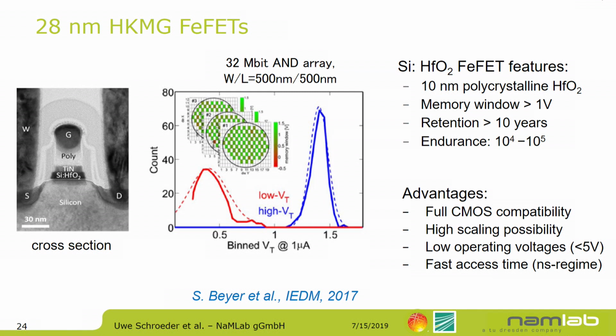And GlobalFoundries did this on 300 millimeter wafers together with Fraunhofer here, and showed that on 300 millimeter wafers you form this nice transistor structure, and you have a good memory window. The green color would be a memory window above 1 volt, nicely across the whole 300 millimeter wafer for all transistor structures, and you have a clear separation for the two threshold voltages for all the structures.